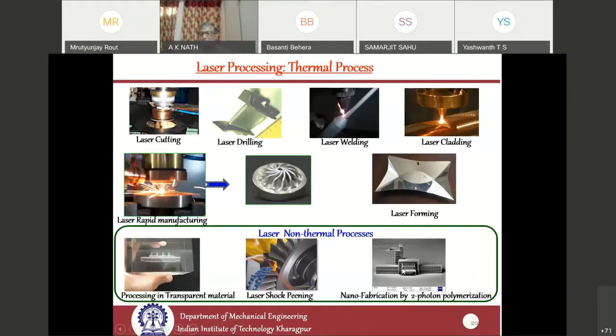So this is the entire main building of our IIT complex, a 7-story building, made in less than a millimeter dimension—of the order of around 500 microns—seen under a scanning electron microscope. And you can see, with almost 10 nanometer resolution, you can build this by the two-photon polymerization effect.